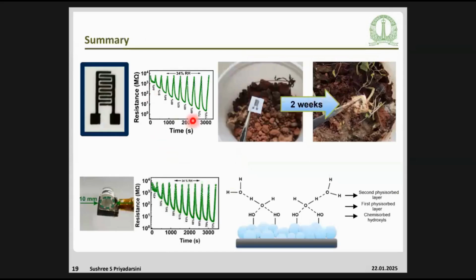Now, this is the summary slide where we have printed one humidity sensor, and the performance was pretty good. After 2 weeks, we have also seen the degradation mechanism, and it's also performing very well when it is in bent condition. The strain was 2.5% in the structure. And then this is the mechanism it followed.